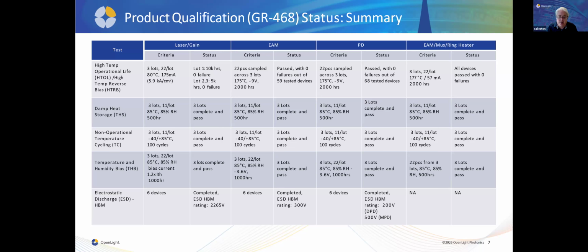And typically we run an HTOL cycle with multiple lots over multiple hours. We regard 2,000 hours as the basic stake, and then we push devices longer. But we also do damp heat storage, temperature cycling, humidity bias, and ESD. So once you define a device with this platform, it can be handled and it will be reliable in the field.